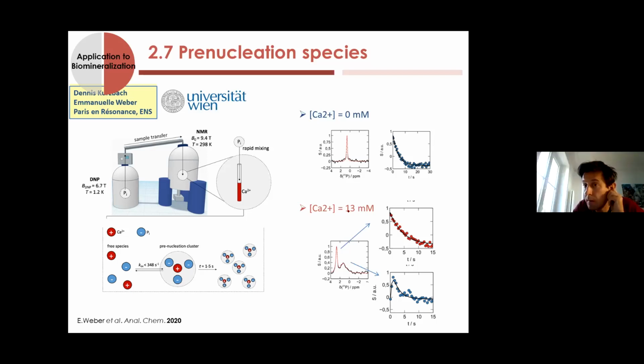Yeah, that's an excellent question, because actually we are really trying at the moment to determine this in that case. It's not tricky, but it's not so obvious, because the limit, I would say, in the liquid state is actually the detection - are you able to detect the resonance? Because as soon as you are increasing the size of your molecules, of course you are limiting the reorientation, and that means you are decreasing the relaxation, and then you are broadening your signal. So that's really the limit.